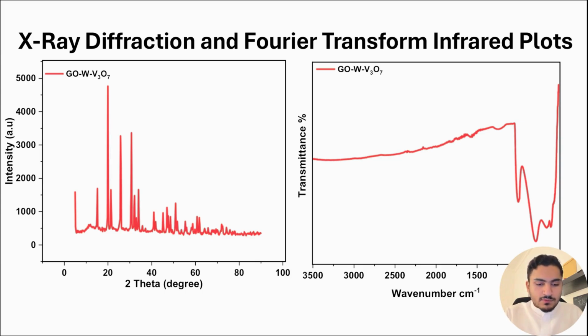On the left, we have the XRD with the most intense peak at about 21 to 22 degrees, indicating successful doping of graphene oxide and tungstate in the vanadium oxide. Additionally, we have several sharp peaks indicating the crystallinity of the material. On the right, we have the FTIR, which shows the functional groups in the material. We have a peak at a wave number of around 750, referring to the graphene oxide. And on the left side of the plot, we have smoothness, referring to the dehydration of the material.